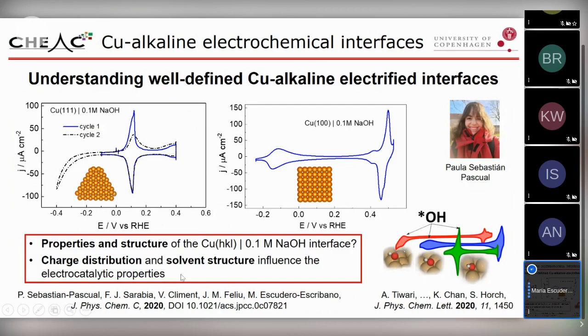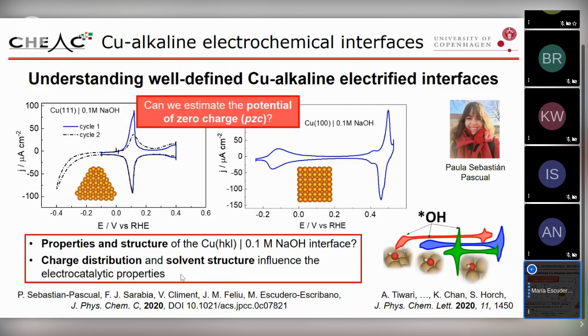So what we really want to understand, and that's why we decided to go for single crystalline surfaces, is what the properties and the structure of these copper single crystals are at the sodium hydroxide interface. And we want to gain information on the charge distribution and the structure of the solvent, because we know that that influences the electrocatalytic properties. So a parameter that is very related to the charge distribution and the solvent structure is the potential of zero charge. So can we estimate the potential of zero charge of these surfaces? It is something that hasn't been done for copper single crystals in sodium hydroxide.